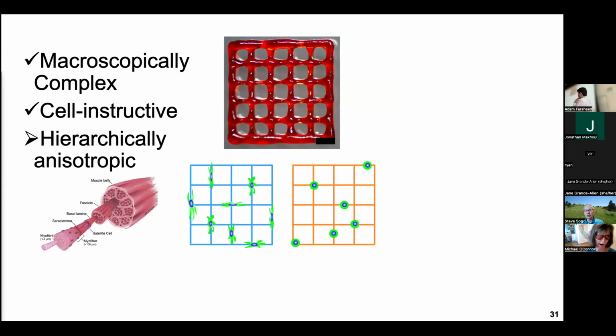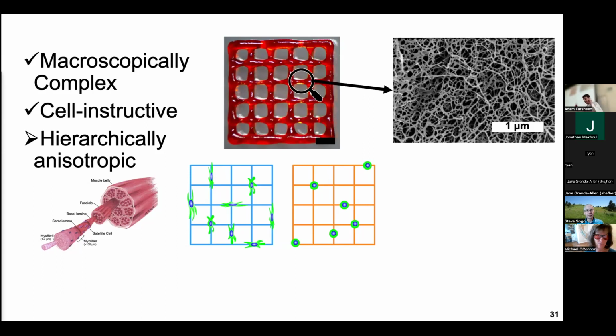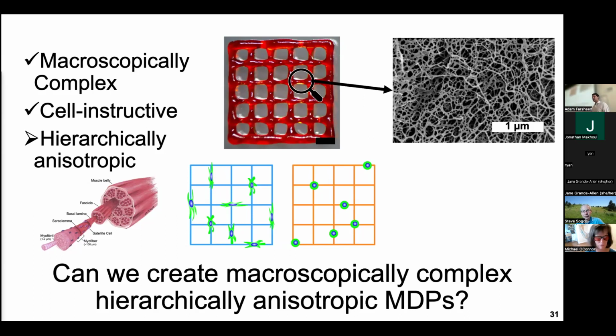But are these hierarchically anisotropic? The answer is no. If we zoom in on the nanofibers within this system, contrary to what I expected when I was starting to do the study, I thought that the fibers would maybe start to align, but we see no nanoscale fiber alignment in our system. And so the next pursuit was to create macroscopically complex, hierarchically anisotropic MDPs.